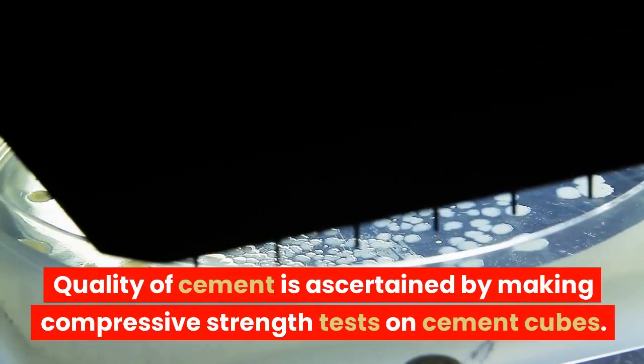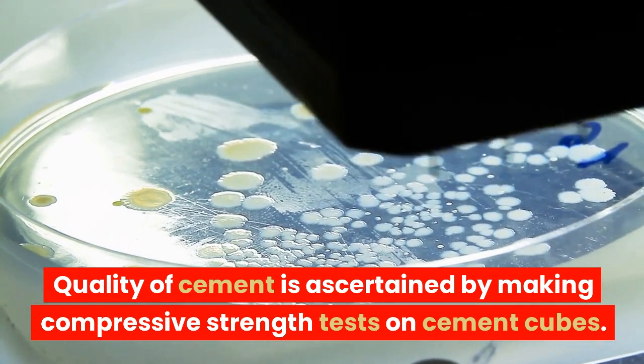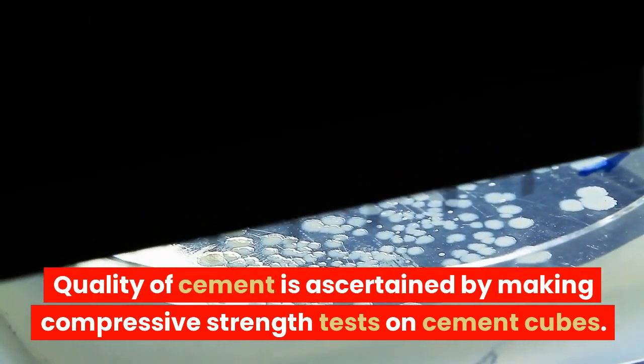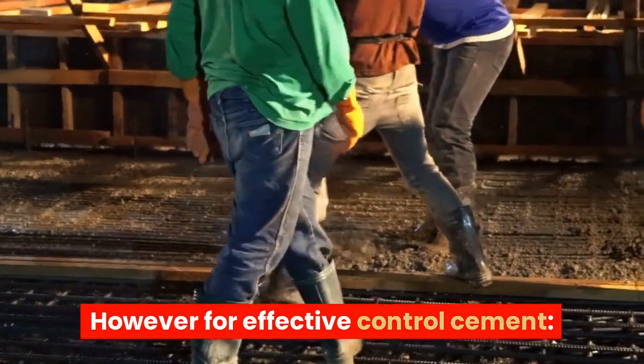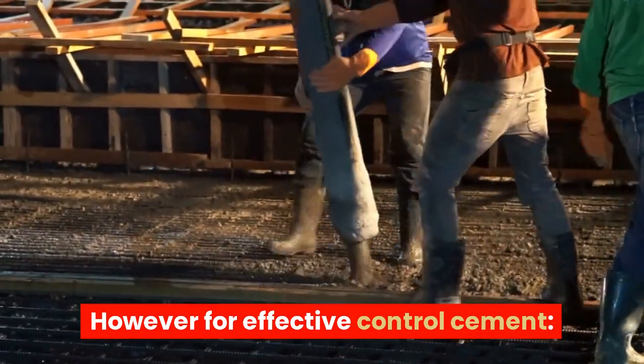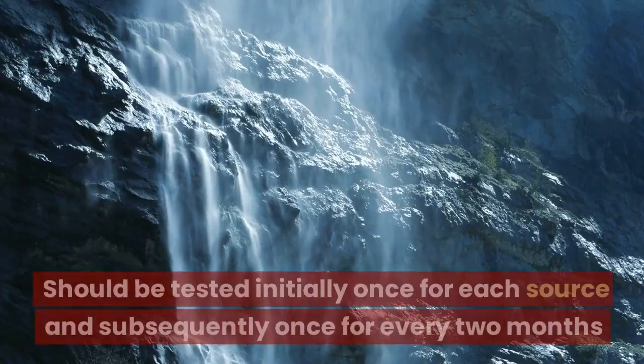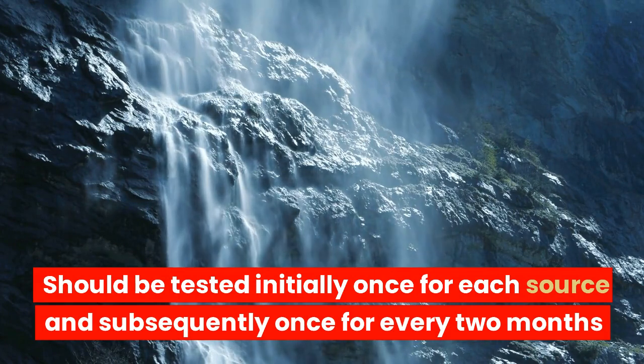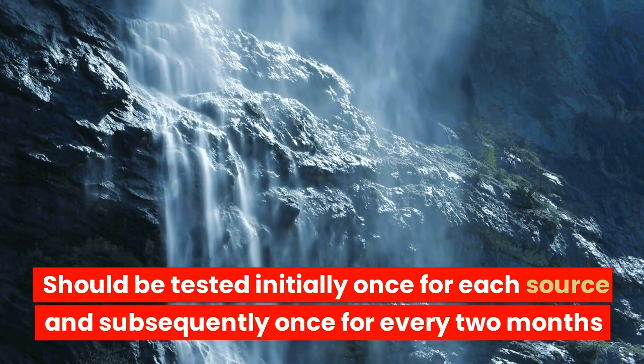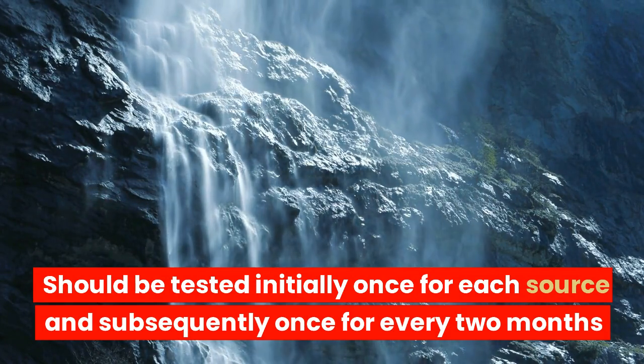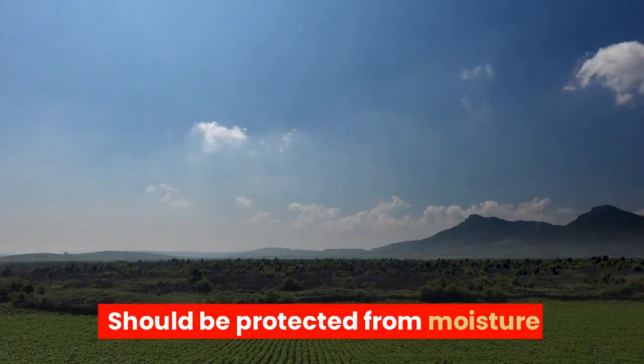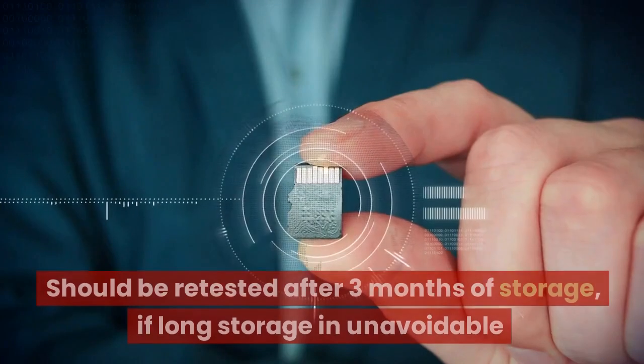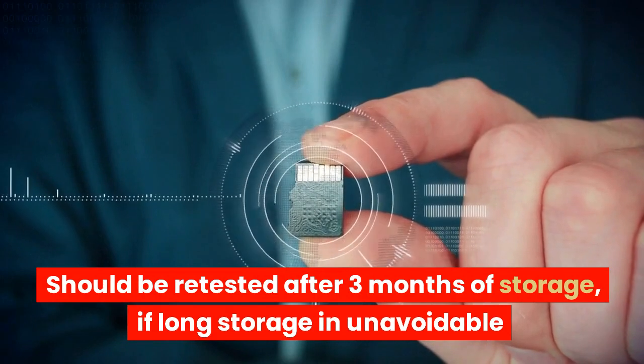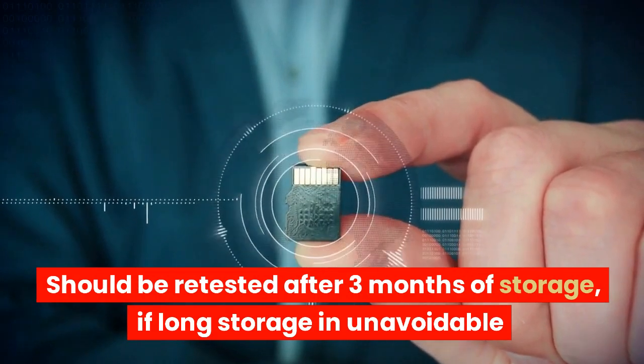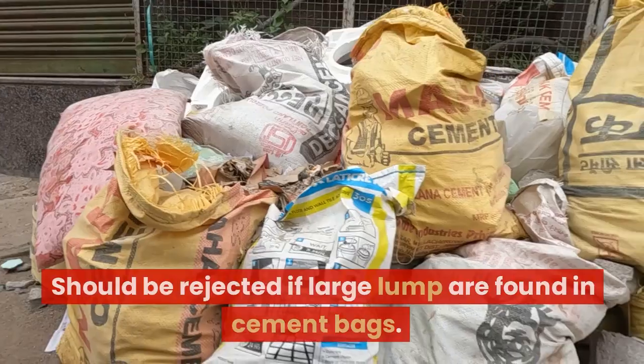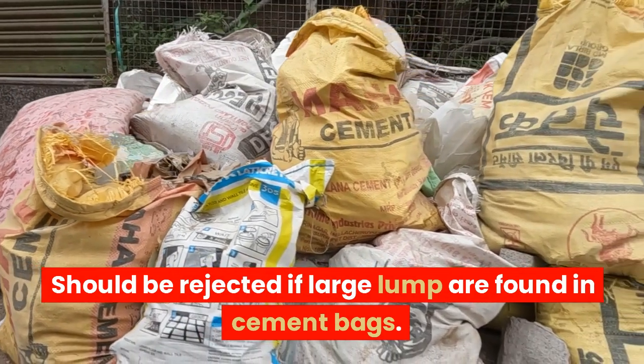Quality of cement is ascertained by making compressive strength tests on cement cubes. However, for effective control, cement should be tested initially once for each source and subsequently once for every 2 months. It should be protected from moisture. It should be retested after 3 months of storage, if long storage is unavoidable. It should be rejected if large lumps are found in cement bags.